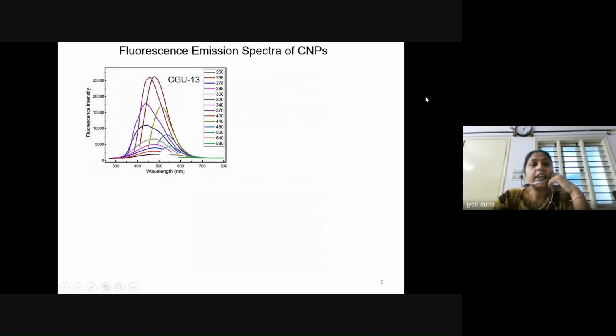Now, we checked the fluorescence emission spectra for these CNPs, and we observed that these CNPs show an excitation wavelength dependent emission profile. You can see in the figure that we have checked different excitation wavelengths from 258 nanometer to 580 nanometer, and the emission from these carbonaceous nanoparticles first increases with the increase in excitation wavelength, and it further decreases after 370 nanometers. So around 370 nanometer, we observed the maximum fluorescence emission intensity. And beyond 580 nanometer, they are not at all emissive, and we are not seeing any emission from this.